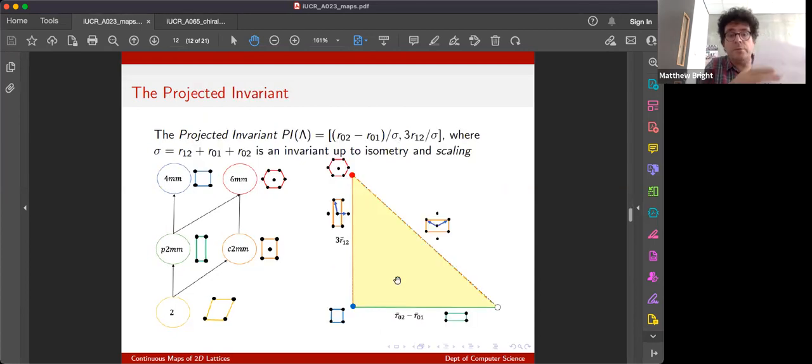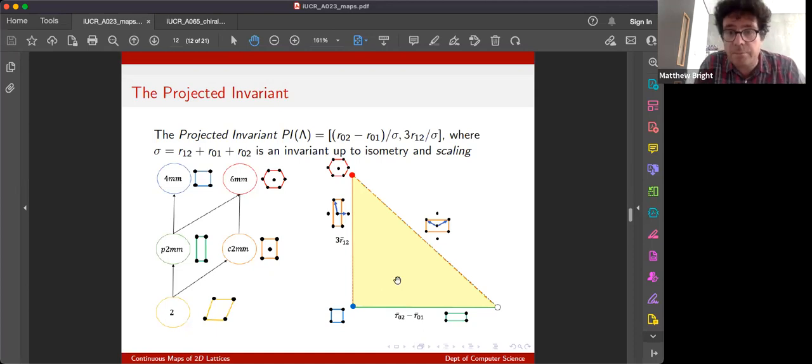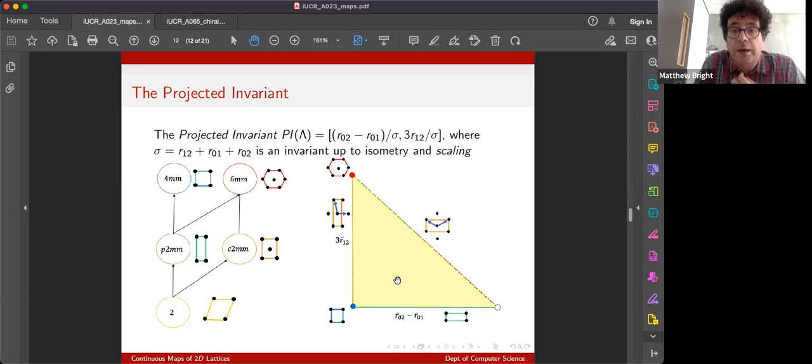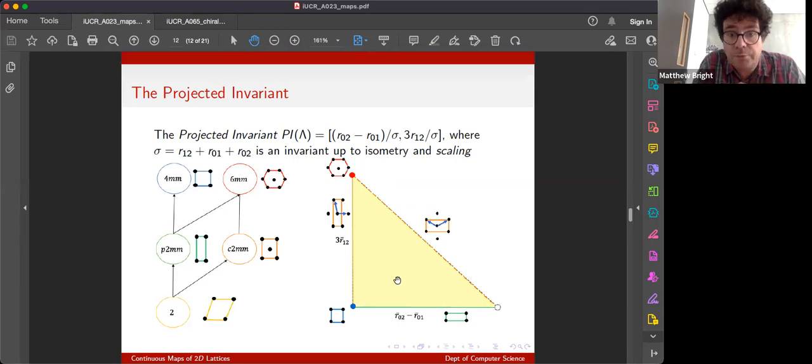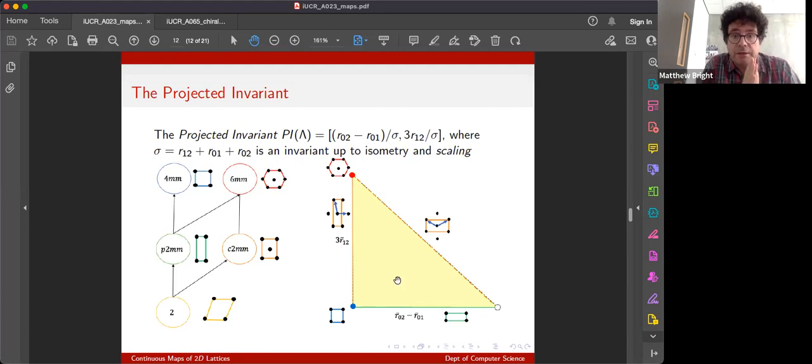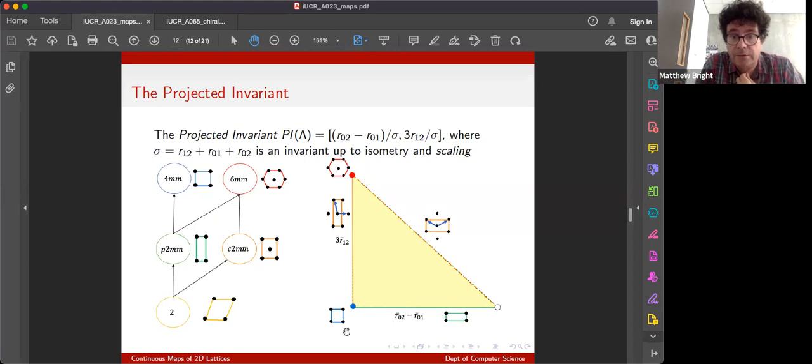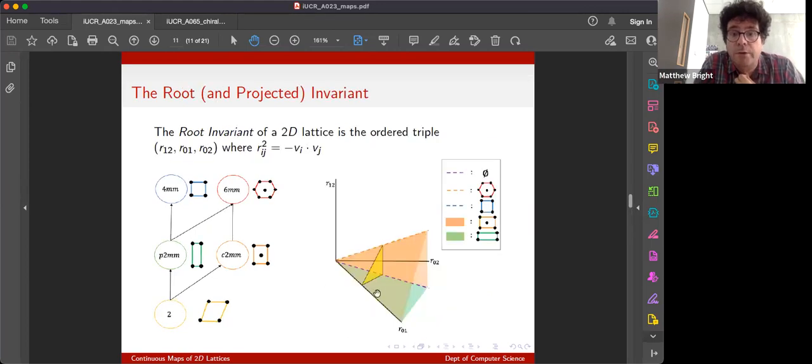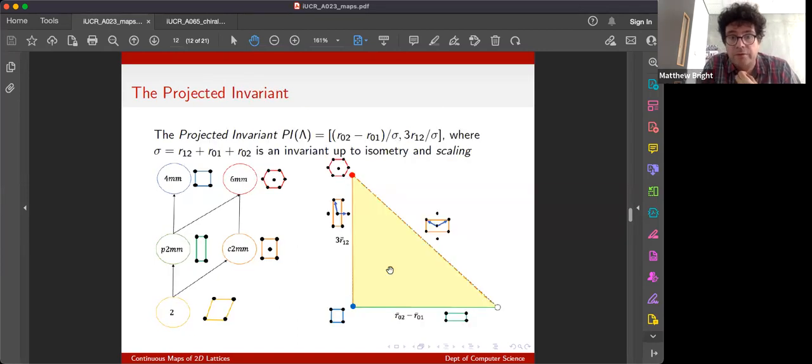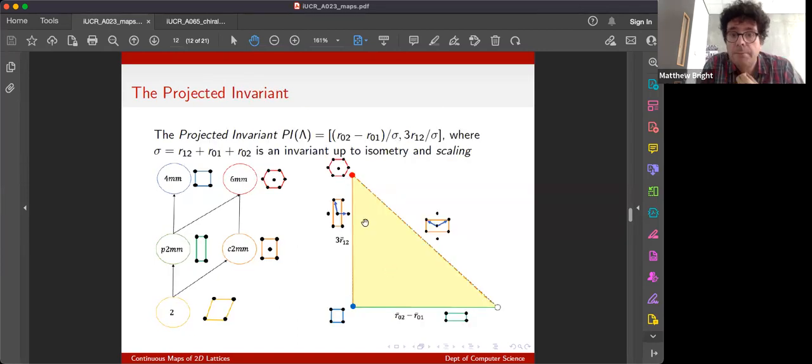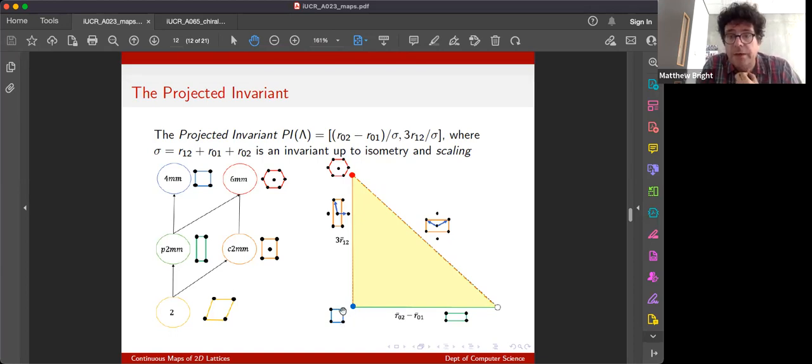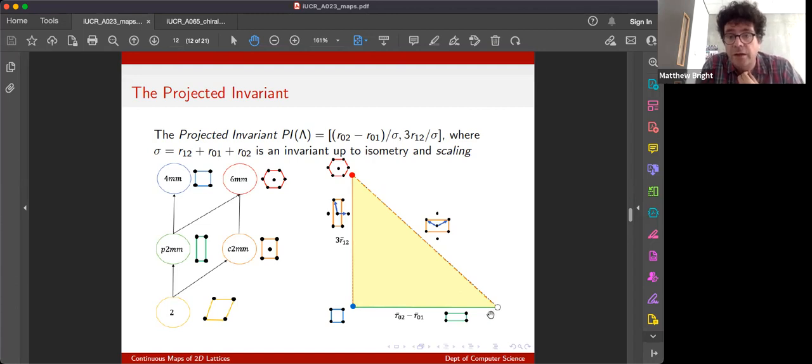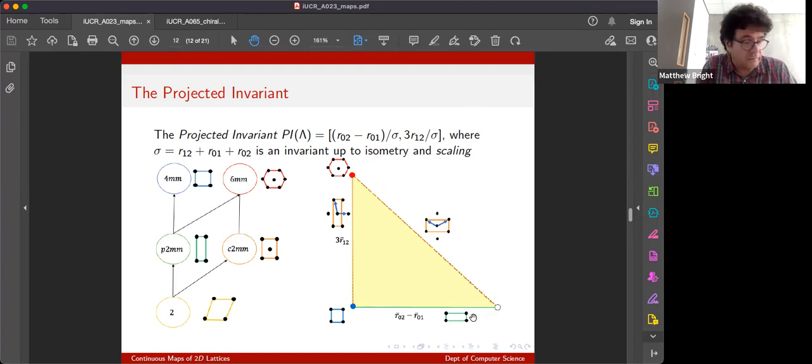And that's rather hard to visualize in three dimensions, so we might maybe want to put it down to two dimensions, which we can do by ignoring scaling. So if we just care about the geometry, we don't care about scaling, we can map this down. And the mathematics of this gets us to a map in a right angle triangle. All we're really doing really is mapping some vertical slice through this cone. But again, the same thing happens. The space is a triangle, now up to similarity. The boundaries and intersections of the boundaries are where higher symmetry lattices exist.